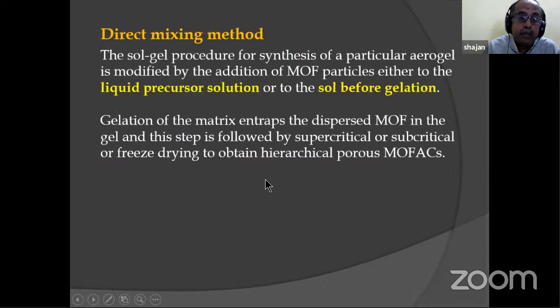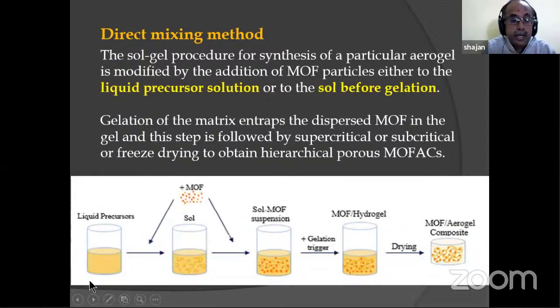The direct mixing method is a simple method. We take the liquid precursors needed for preparing the aerogel, then you add the MOF to this, then you prepare the sol. Or you can add the MOF at the stage when the sol is prepared. In both ways you can do. Now you will have a sol MOF suspension. Then you gelate it, condensing it by using the gelation procedures. Then you will get a hydrogel. Then you can dry it.